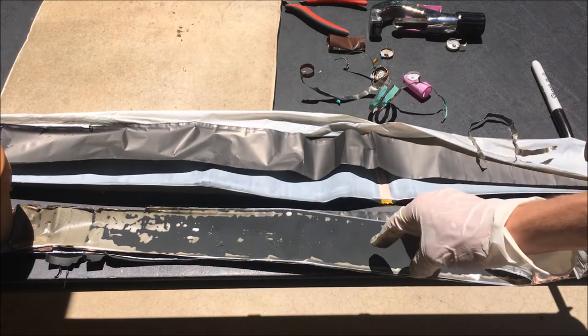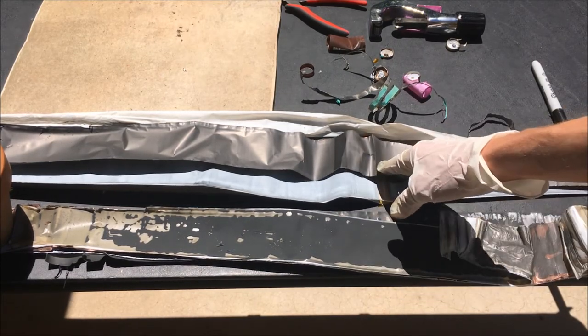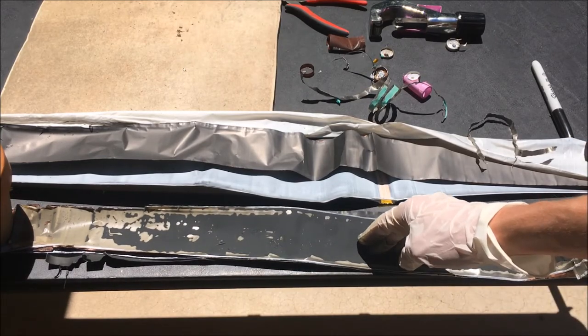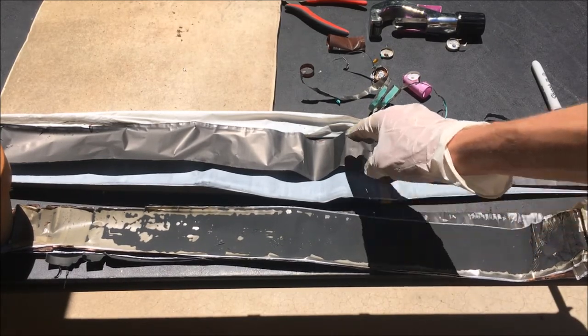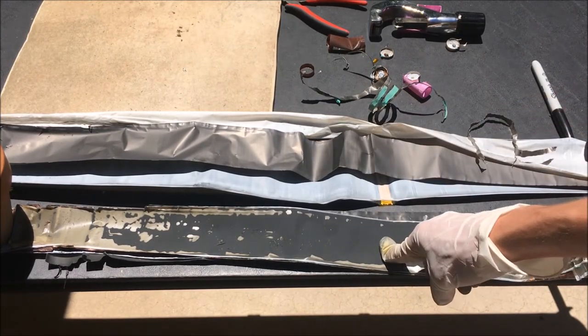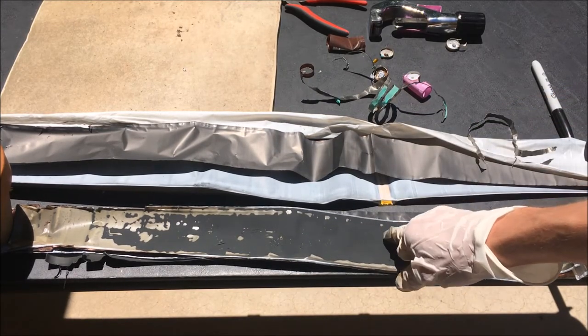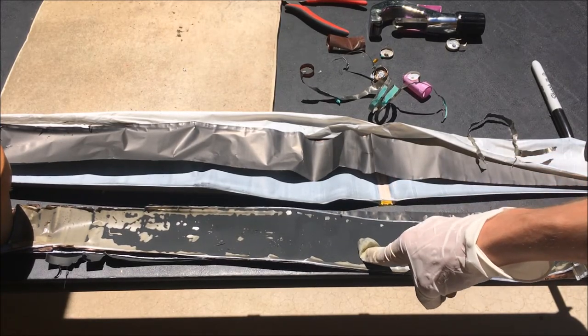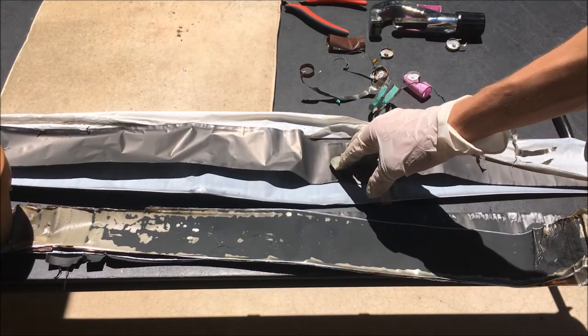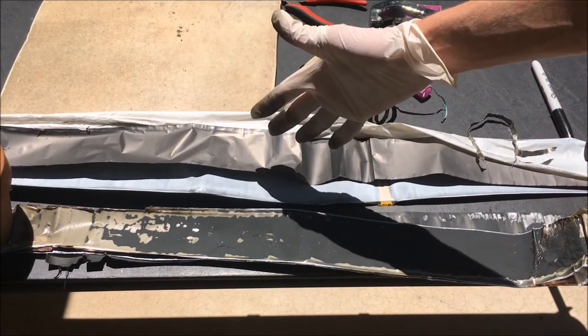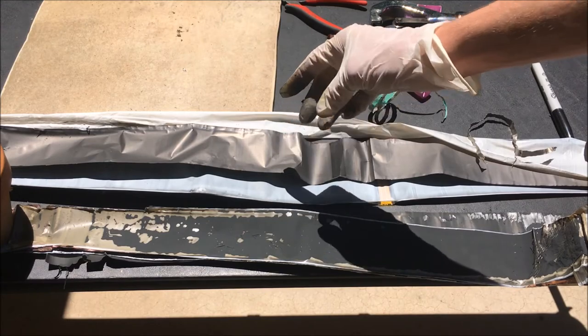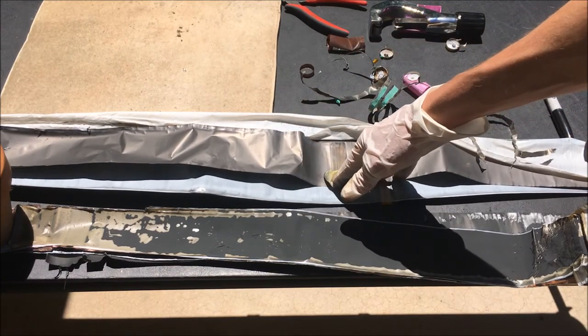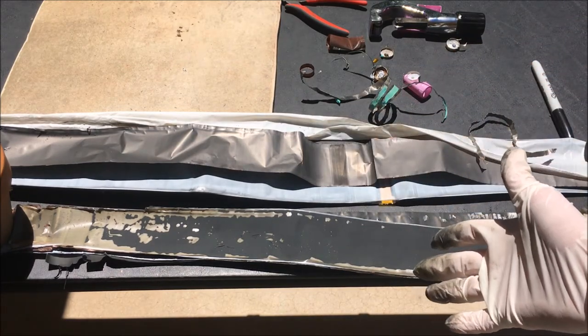Overall, it's fairly evident that the cheap knockoff cell—or not even knockoff, just the no-name cell—is of an inferior quality. Surprising that the capacity was comparable to this considering how much less active material it is. Maybe that's accounted for by the thicker, more deep material than this one. But definitely lower—well, not that much lower capacity, but lower performance and much greater internal resistance on the cheap cell than on the much thinner, more readily conductive and readily traversable by ion separator in the expensive cell.